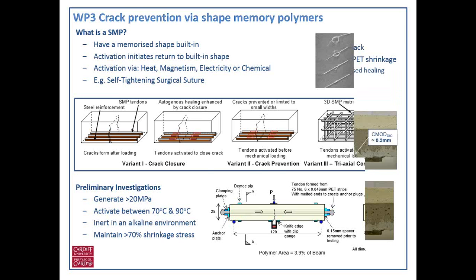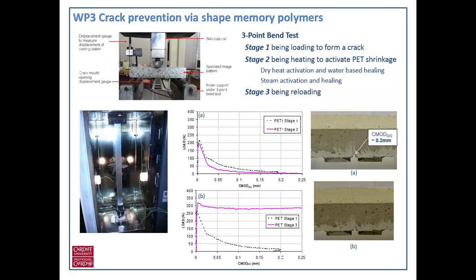So if we go on to the next slide now, we have been able to use these systems to close early stage cracks in concrete. Cracks that were first of all created using a 3-point bending test, and then the polymers were activated within the concrete to then close cracks. So we've proven this system works from a conceptual point of view and also from a small sample point of view. What we're doing now is upscaling that and looking at different forms of the polymer, whether it be strips, whether it be bars, whether it be strands, and looking at the best way of implementing it.